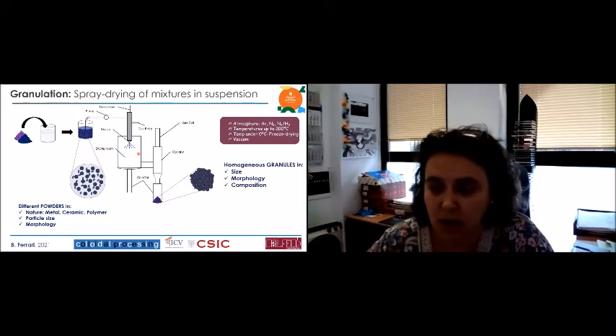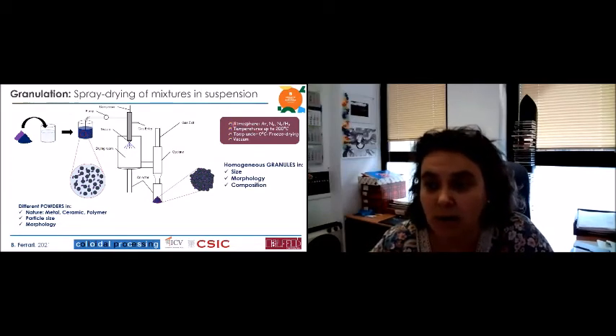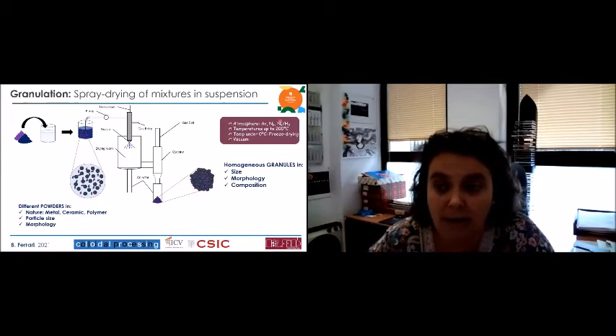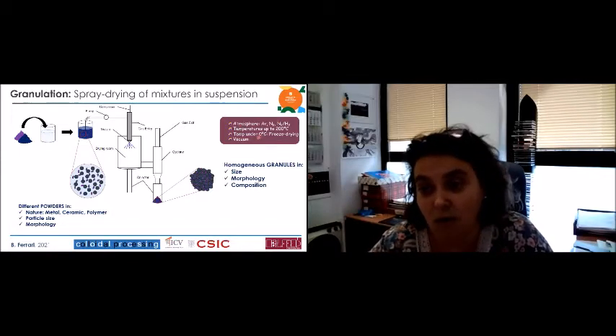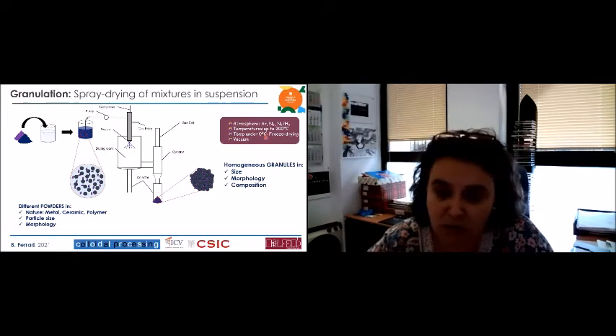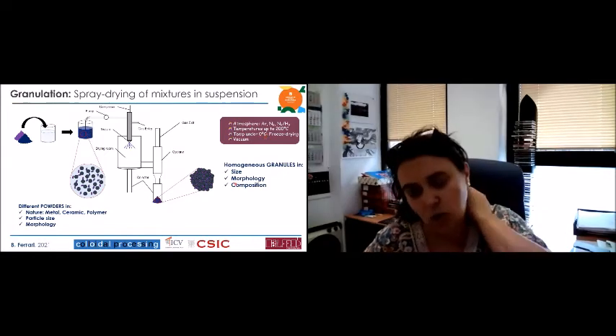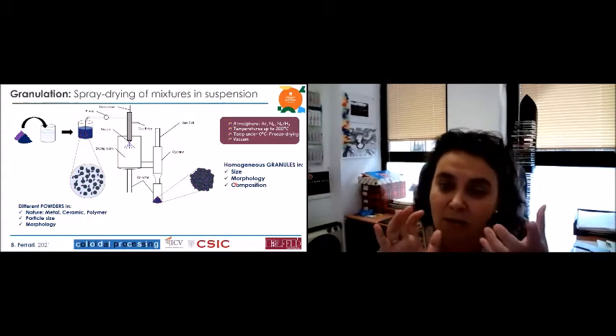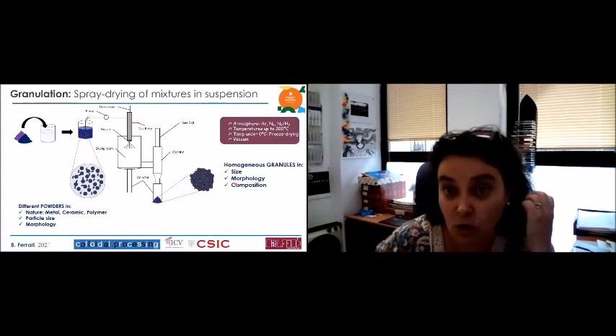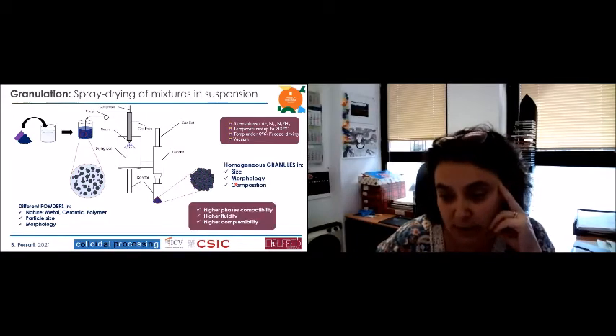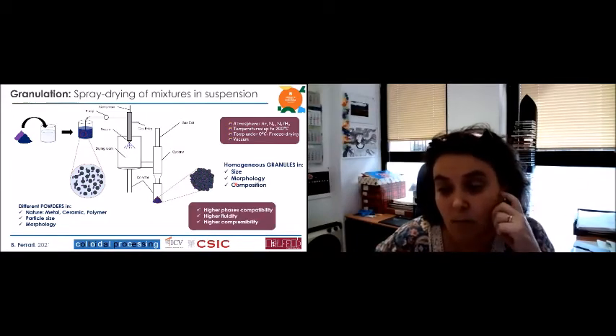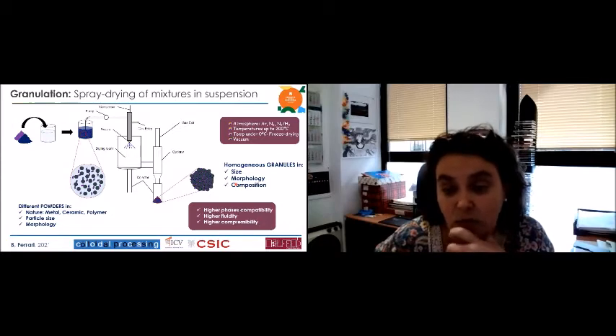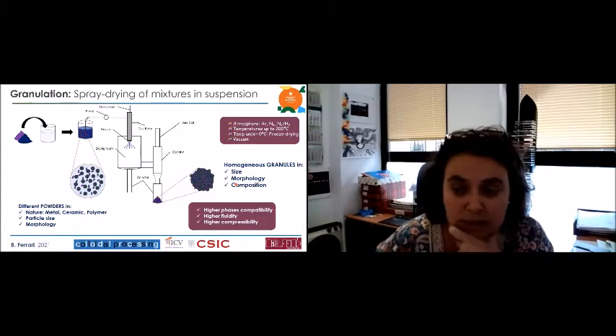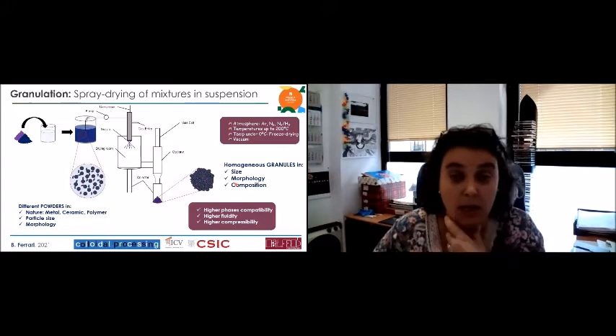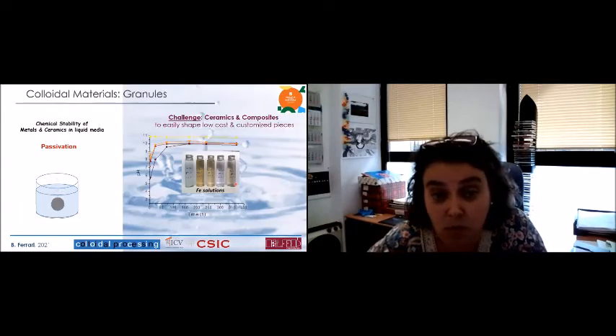that you can manage in morphology and composition, right? And in the chamber, you can work in different kinds of atmosphere and temperature, even under 0 degrees, that means doing freeze drying, or in vacuum, right? So you have many possibilities to produce this kind of granules that you can use in additive manufacturing to make the phases more compatible, increase the fluidity of the powder, and also, with the fluidity, the compressibility of the powder, right? So this is an important thing that we, people devoted to colloidal processing, used to use.